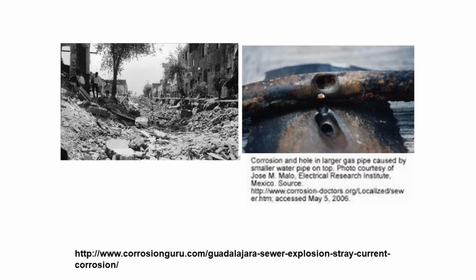Okay, so then you have the very serious problem that you have a hole worn also in the petrol pipeline, which allowed the sewer to fill with petrol, and then sometime later the petrol fumes accumulated in the sewer ignited and caused this explosion, producing a trench up to about 6 meters deep and about 2 kilometers long, and causing a great deal of destruction.